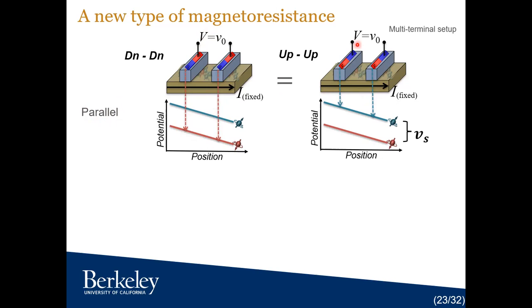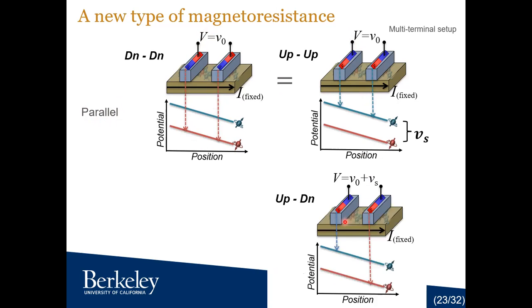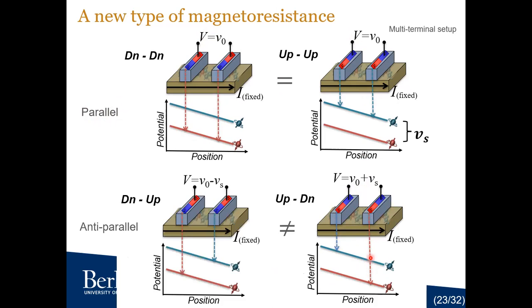But let's look at the anti-parallel states. When the left one is up and the right one is down, the left one will measure this blue curve, the right one will measure this red curve, and the voltage difference will be this offset plus the spin voltage, this difference. If you look at the opposite case, where the left magnet is down and the right magnet is up, now the left magnet will probe the red curve and the right magnet will probe the blue curve, and the voltage difference will be offset minus the spin voltage. So these two are unequal. The anti-parallel states become unequal.